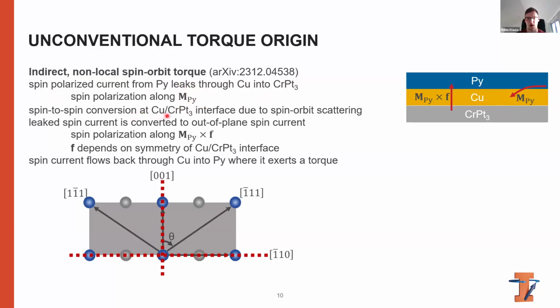Then at the copper chromium platinum 3 interface, we get spin-to-spin conversion due to spin orbit scattering.